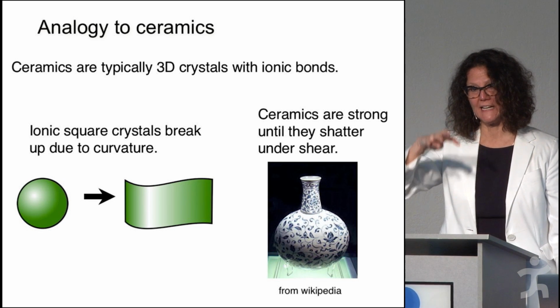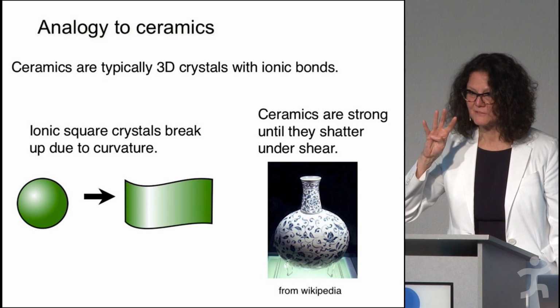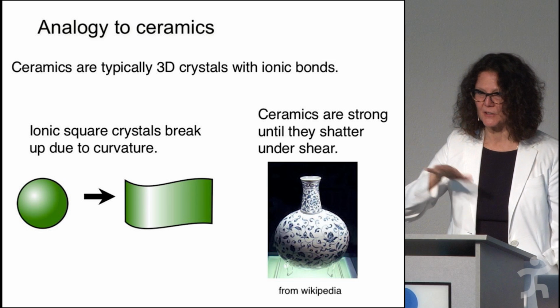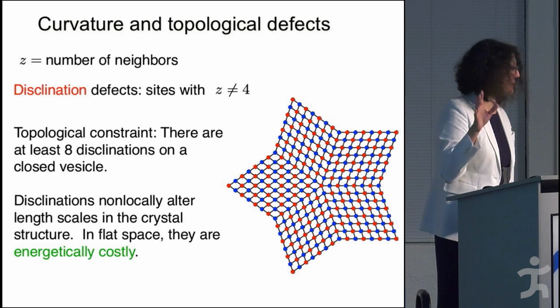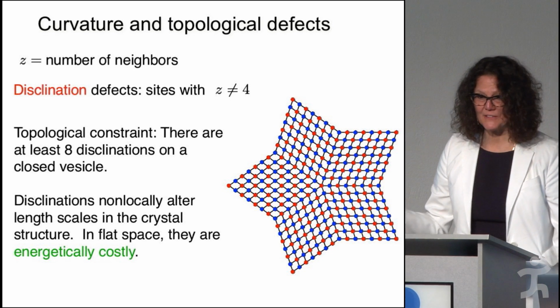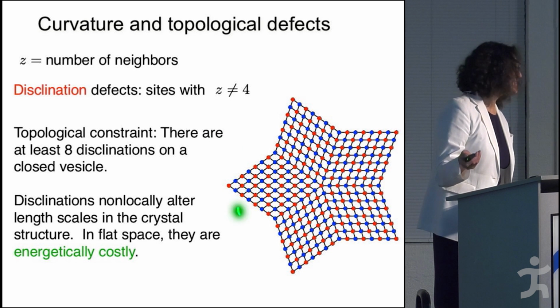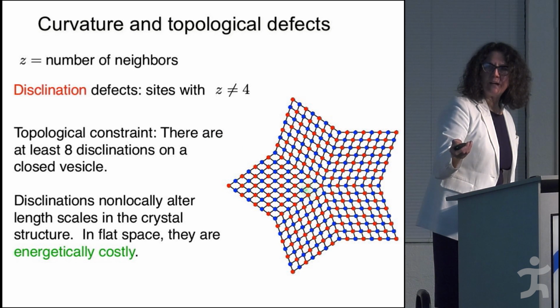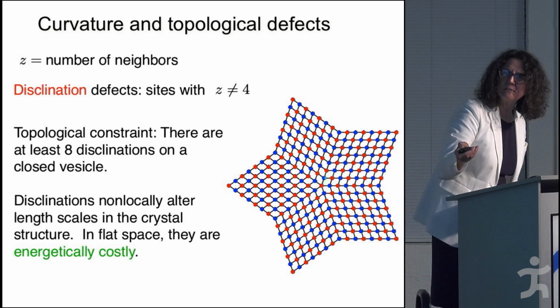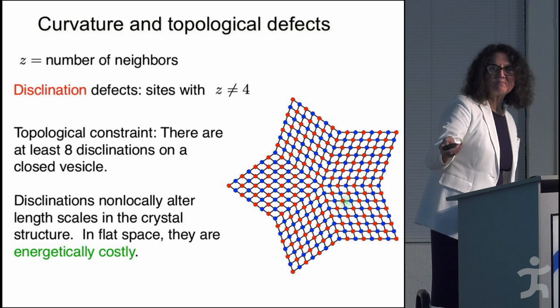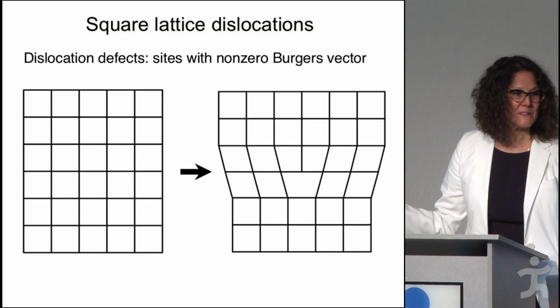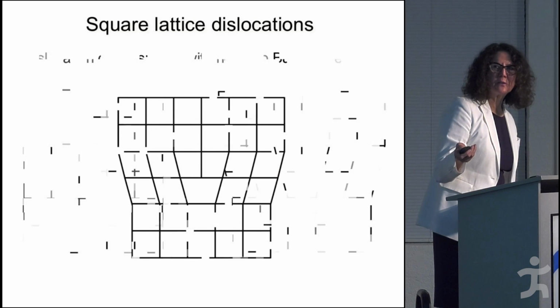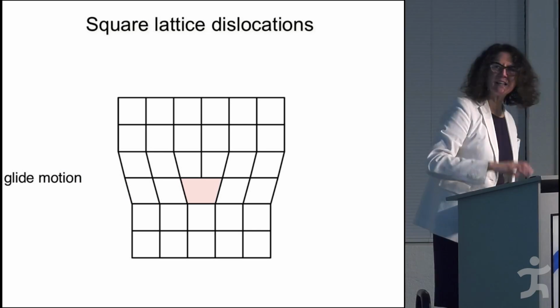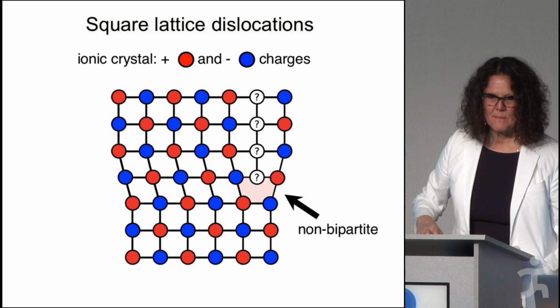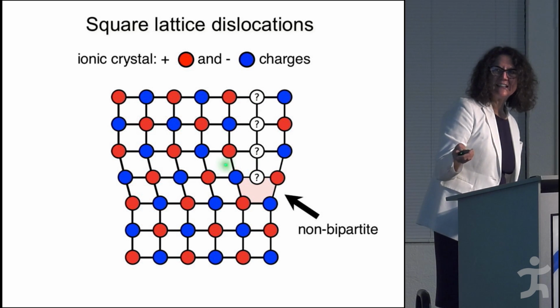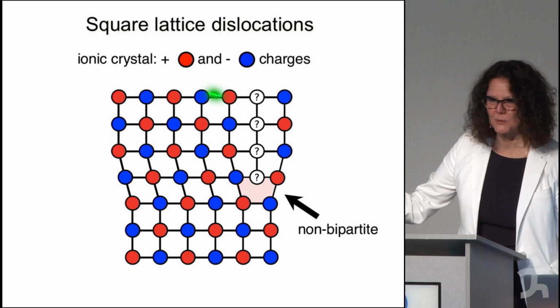If you have a square lattice, how many neighbors do you have? 4, right? So defects can have 3 neighbors or 5, okay? And they have to be close. But if they are ionic and they have some stoichiometry of neighbors of charge, it's going to be very difficult to form these defects. This one is with 4. This is 4 and this is 5. 1, 2, 3, 4, 5. And it looks like it's reasonably ordered, it can occur. The one with 3, which is the minimal one, has to have 3 neighbors. They are very difficult to form. Generally, to be something plastic that has defects, the defects glide and behave nicely. But when you have charges, how do you put in the defect so that you don't violate a red having a blue around it? It's impossible, right?